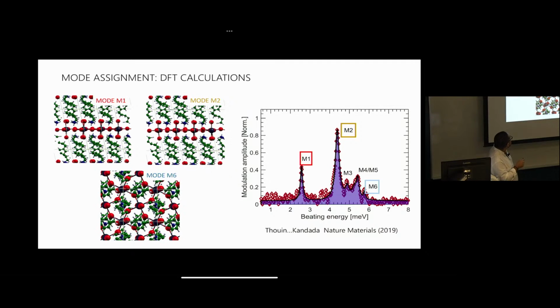And so we know that these are all lead iodide and the lead iodide plane modes that involve some sort of rocking as well as twisting of the octahedral units. This M6, which is this one over here, has slight out-of-plane motion as well of the octahedral. So all in the lead iodide plane, M6 a little bit out of plane, and that's going to be important in some of the data that Esteban is going to show us in a minute.